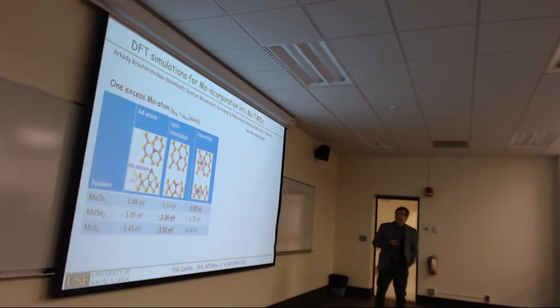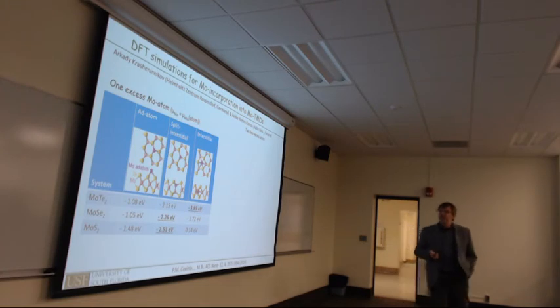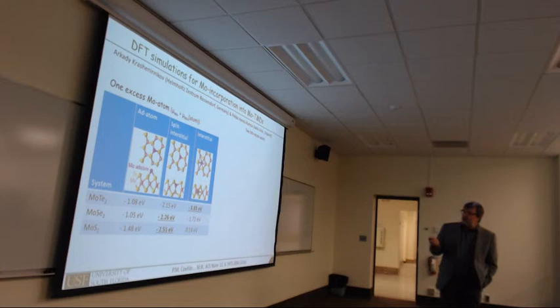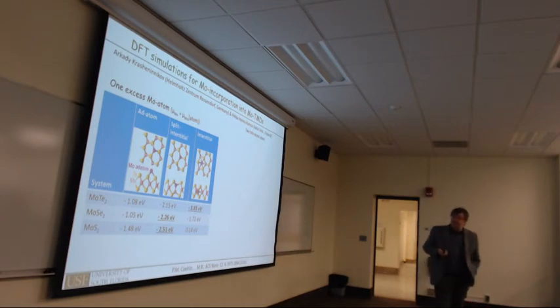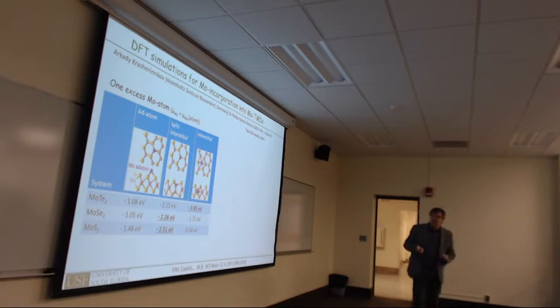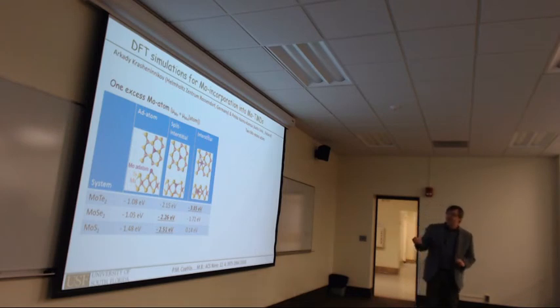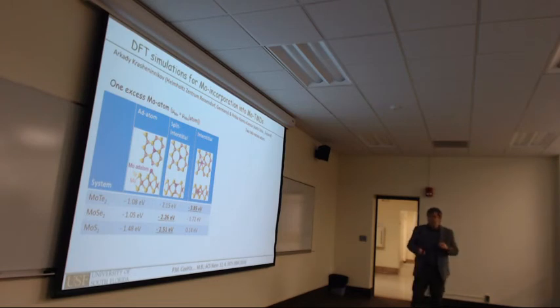Now, to understand that better, we asked Arkady and Tanu to do some DFT calculations to see what the energetics are. And so they considered excess molybdenum on the surface, and they considered 3 different configurations. One is just the adatom on the surface. The other one is put an extra molybdenum at the side of a molybdenum, so you form what they call a split interstitial site, where you have 2 molybdenum atoms at the site of a molybdenum, or an interstitial molybdenum, which is in the center of the hexagon, just within the plane of the molybdenum.